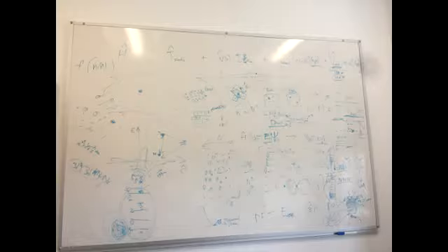So this is what DFT is about. And there are a bunch of different approximations for these guys. So some of them are called LDA. This is the simplest one. So this is called local density approximation. It takes the form of this guy to be equal to an explicit analytically known expression for free electron gas. So when the n is almost flat everywhere, then you can solve it analytically. So local density. The next approximation is called GGA. It's a generalized gradient approximation.